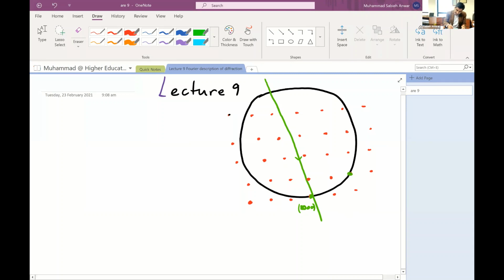So this means that a crystal is placed at the center of this Ewald sphere, and scattered X-rays emerge from the crystal and go in the particular direction of the reciprocal lattice point that is intersecting with the Ewald sphere. And this angle here is my 2 theta angle, and half of this will be the grazing angle or the angle of incidence for the X-rays. And I can also identify the index of this reciprocal lattice point, which will correspond to a family of planes. So this is the Ewald construction.